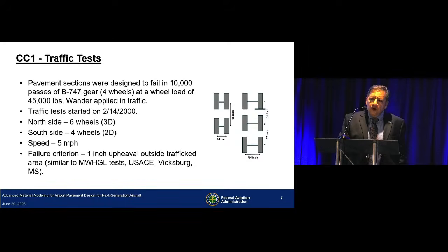Traffic testing started on 14th of February in 2000, which happened to be Valentine's Day. The north side was tested with a 6-wheel gear, and the south side was tested with a 4-wheel gear, and this figure shows the wheel spacing and the axle spacing for the loading gears. The test speed was 5 miles per hour because for airport pavements, the most damaging condition is when the aircraft moves from the gate towards the runway. So testing at slower speeds is more desired. The failure criterion for flexible pavements was 1 inch of upheaval outside the traffic area, signifying shear failure in the lower layers of the pavement structure, especially the subgrade.